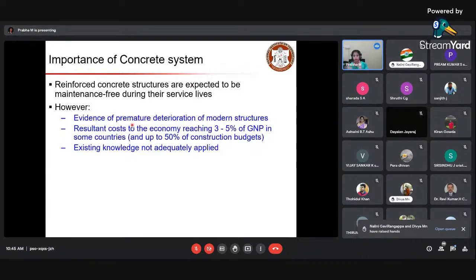So you tend to observe a lot of cracks with stain marks. You might have observed this in many of these structures. If the crack is there, and it is continuously there without repairing it, it is going to go deeper and deeper to reach the steel surface, and it is going to start corroding, and you see a lot of rust formations or stains on the concrete surface.